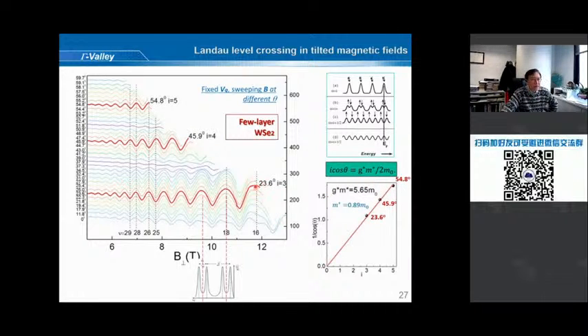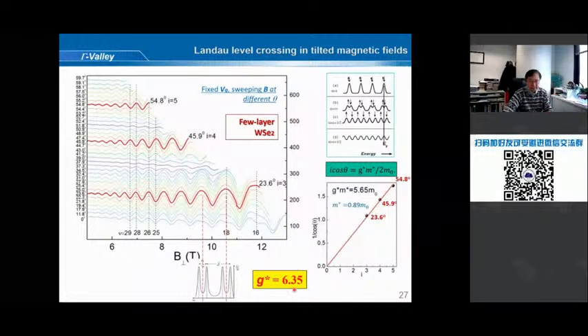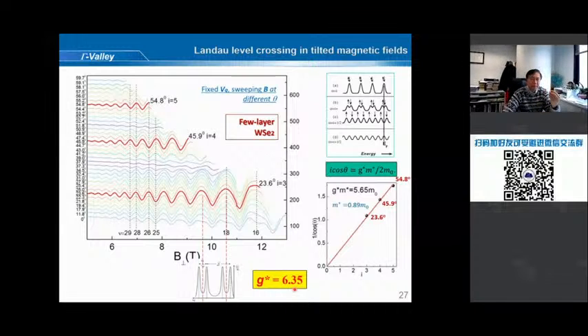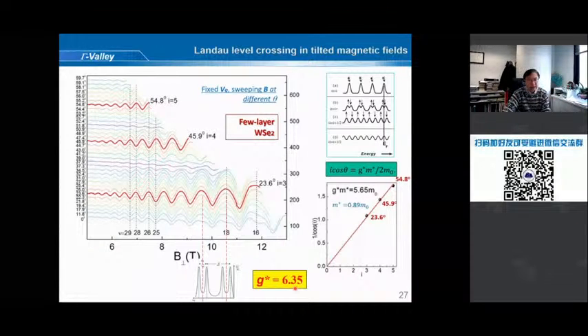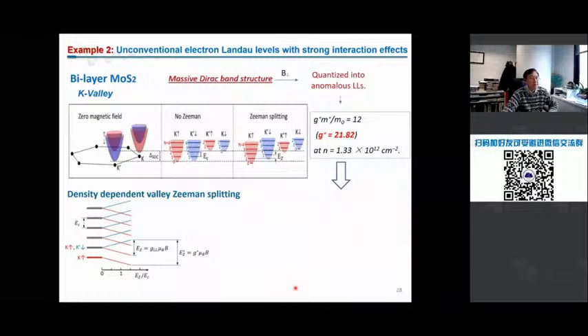If I assume the first crossing angle is I equals 1 and 2, 3, and then plot it in these simple relations, it's not a linear line and doesn't cross the 0 point. Now, unless you put this, the first crossing point is 3, and 4 and 5, they perfectly align to each other. So in this way, you determine the G factor. It's about 6. So the single particle picture is 2. That indicates strong interaction behavior in this kind of materials.